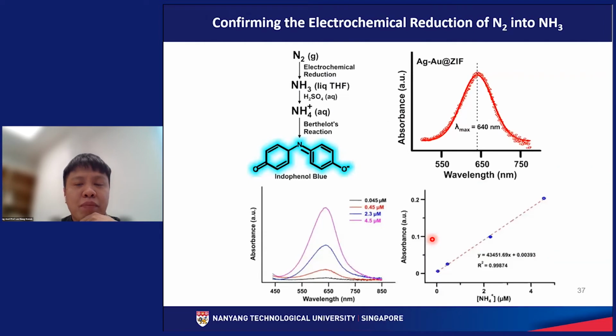So we subsequently confirm the electrochemical reduction of nitrogen into ammonia by quantifying the amount of ammonium present in our system. So we do this using the indophenol blue method, whereby we convert ammonia into ammonium and subsequently into indophenol blue, which is a blue dye. So after which we can quantify the ammonium present by quantifying the characteristic peak of indophenol blue at around 640 nanometer. So this is the calibration curve that we can use to quantify the amount of ammonium present.